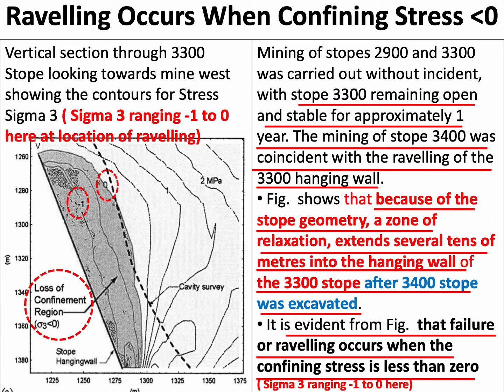And this dotted line is the cavity outline. The cavity was formed from the back, in the back wall, from this to this, in the shape of this dotted line, which exactly matches the zone where the stresses are tensile. These stresses becoming tensile become the cause of loss of confinement in this region. The blocky rock had lost its confinement in this region because of the prevailing tensile stresses in and around them.